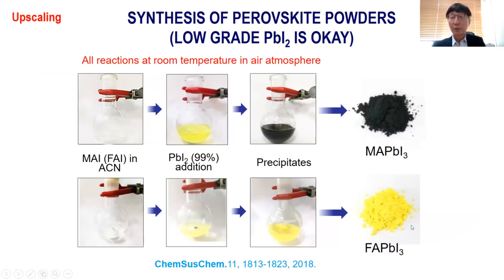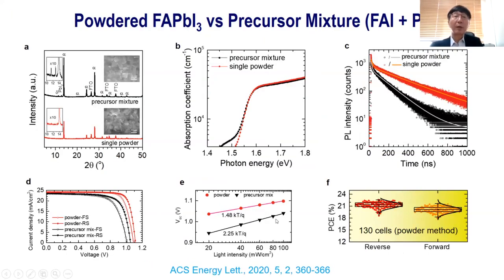You can make the perovskite material FAPbI3 or MAPbI3. The FAPbI3 is not a perovskite structure. This is a delta phase, non-perovskite structure, which can be prepared even at room temperature. And using this FAPbI3, we can get a very highly crystalline perovskite structure without a trace of PbI2, and